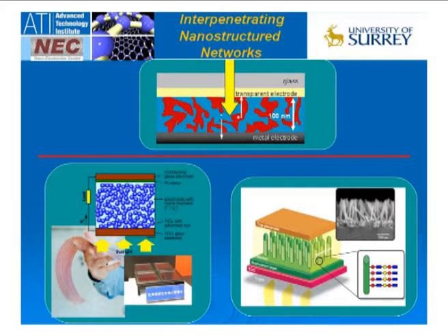And the diagram is, can we create a thin film solar cell where one of the electrodes are three-dimensional rods sticking out, say for instance maybe zinc oxide based rods, and put an organic material on the other side with an electrode on the other side. And this would give you the largest packing density possible of these heterojunctions that can allow efficient charge capture, dissociation, and transfer. And so that is where people are trying to get through using different routes.